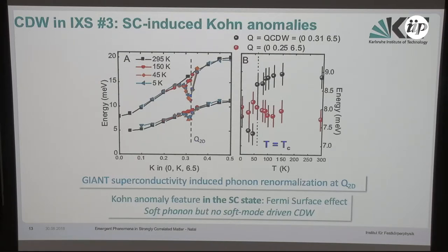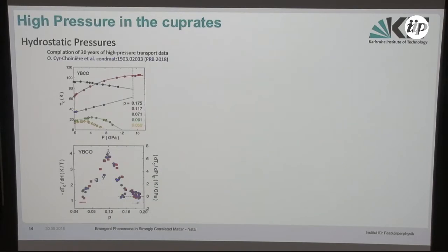Okay, so now I'm going to use these three signatures of the CDW to try to study the interplay between the charge density wave and superconductivity using pressure. We first start with hydrostatic pressure. It's well known that the critical temperature of YBCO depends strongly on the pressure, and it's very different depending on the doping.